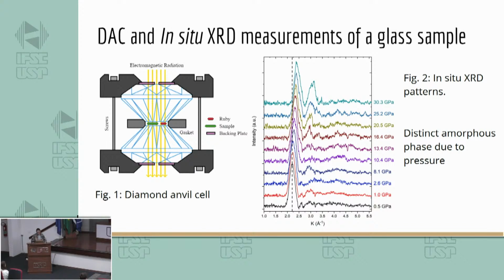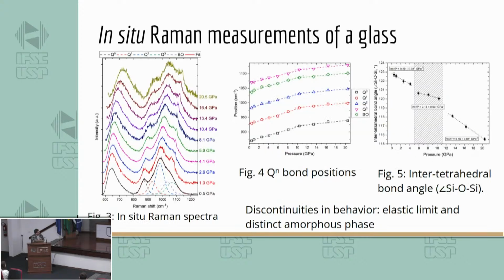And in this example, we had the X-ray diffraction of the glass up to 30 GPa. And in here, we can identify a distinct amorphous phase that happens because of pressure. And something else we did on the same study was obtain the Raman spectra, where we can observe the QN species and how they evolve with pressure, and also the intertetrahedral bond angle between the silica species, where we identify some discontinuities which are usually related to the elastic limit or also because of the distinct amorphous phase. For some more details, I invite you to come to my poster and we can discuss this work.